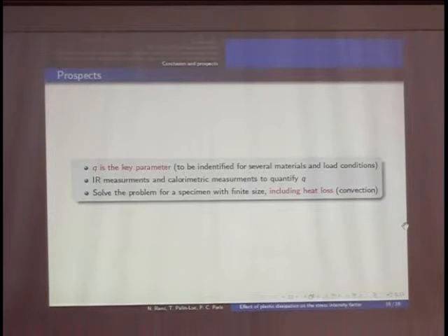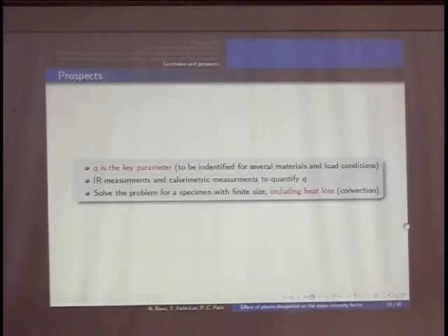I'm somewhat surprised about the large value, because I have tried to use this effect to measure the plastic work, yes? Even at the threshold value. And we have performed experiments at 20 kilohertz in order to measure the plastic work near the threshold. That would be the idea, to see what happens. And the increase in temperature we had very carefully measured in millikelvins, yes, and we had only a few millikelvins, and other